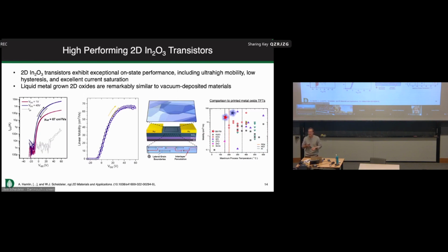So this is very different in so many ways from traditional materials, but at the same time, it behaves a lot like a vacuum process semiconductor. And this is the closest thing. I've worked in a lot of flexible and printed electronic materials before. This is the closest thing I've ever seen to a vacuum process material. I think one of the properties is that it has this unique grain structure. It's carbon free. We didn't introduce any other additives to this material. It's really the reductionist approach to making a semiconductor: you have a metal and you oxidize it.